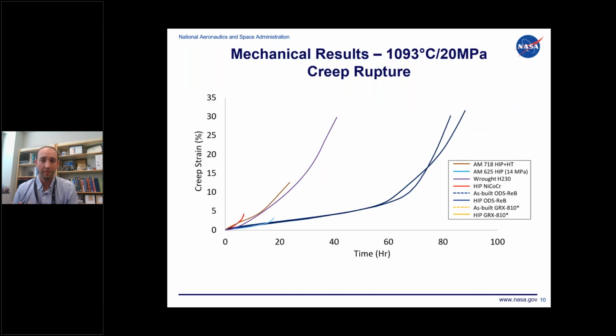So then we started to do creep tests. This is creep curves to rupture at 1100 degrees C, almost 20 MPa, so very high temperature, low stress. That red curve there is nickel cobalt chrome non-ODS, just us 3D printing that nickel cobalt chrome powder. You get a handful of hours, it strains very quickly, and then it breaks on you.